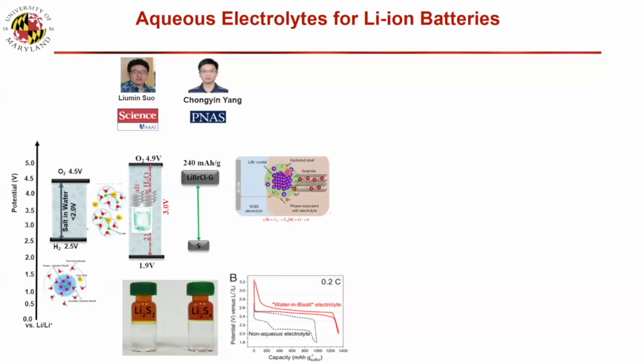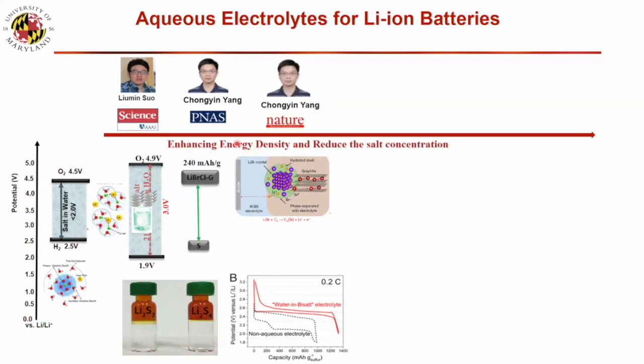But right now we are further using this chemistry in the organic, and we demonstrate that this chemistry can also work in the organic. But we got this knowledge from the water-in-salt chemistry. But this high-concentration electrolyte has a challenge, which is the cost. So we have to reduce the cost. Reducing the cost means reducing the concentration of the salt. If we reduce the concentration of salt, then we cannot form SEI. If we do not form SEI, we cannot extend the window. So we have to add additional salt to form SEI.